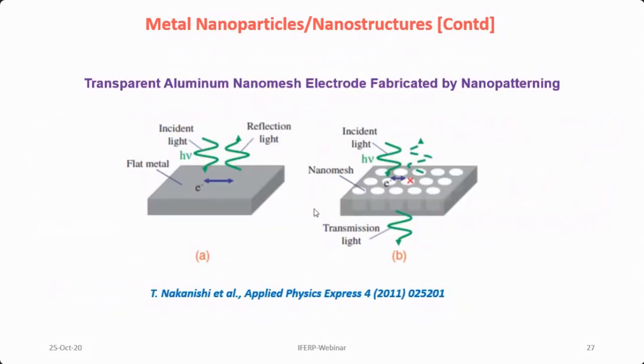This is the example which I was telling about, that one Japanese group created nano mesh. What they have done is they took an aluminum sheet and then they created nano size holes inside it, and to create that they used masking, and then they used silica nano dots on it, and then they did etching, and only the silica nano dot area got etched, and where they have made holes.